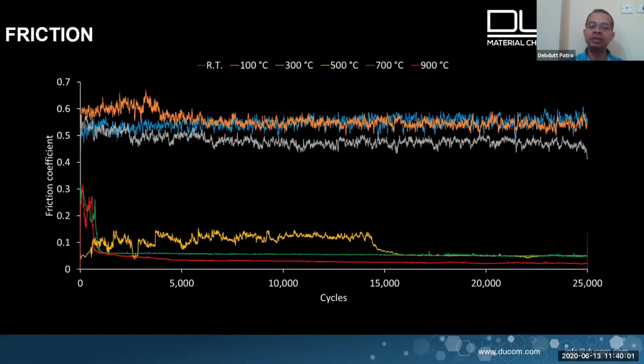So this is the test data which we got at the end of the experiment. And on the y-axis, you actually see friction between these surfaces which are rubbing. And on the x-axis is the timeline or the number of cycles going to 25,000. Starting from the top, the friction coefficients are 0.5 to 0.6, and these are at temperatures up to 300 degrees.